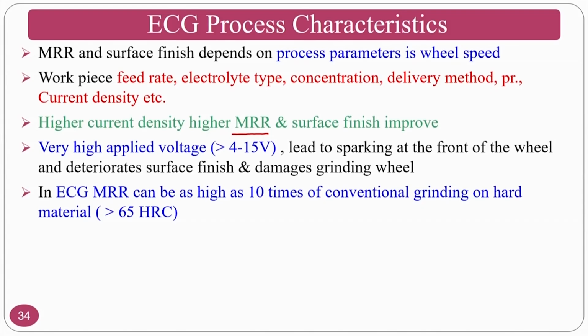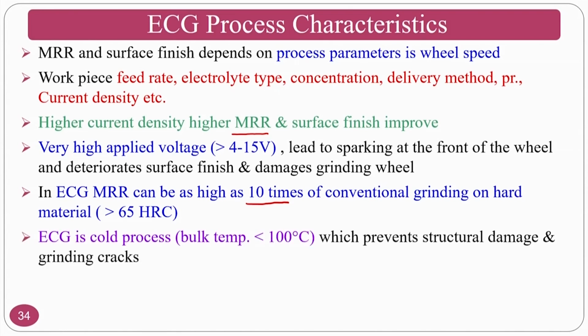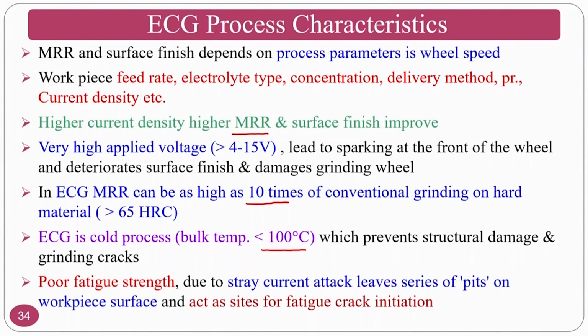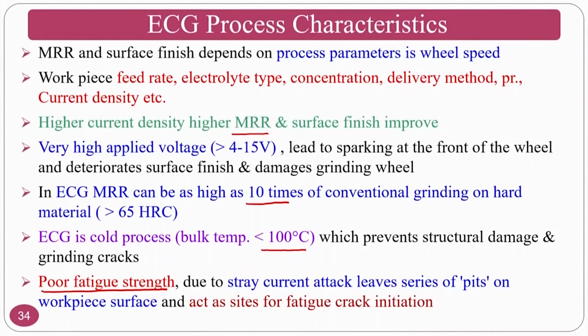Electrochemical grinding MRR can be as high as 10 times that of the conventional grinding process in the case of hard workpiece materials, where the HRC, that is the Rockwell hardness scale, is above 65. Electrochemical grinding is a cold process. Normally the bulk temperature that you are going to achieve is less than 100 degrees. That is why there will not be any metallurgical or structural changes. However, there is poor fatigue strength due to stray current attacks, because of the other wall surfaces there will be stray current formation, because of which there will be poor fatigue strength.